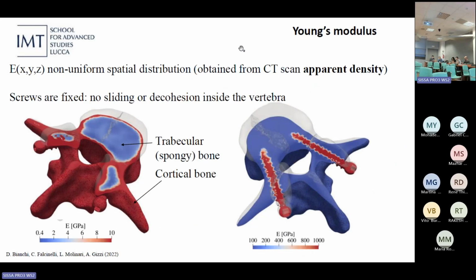Regarding the reconstruction of the Young modulus, this of course is not a uniform material, it is a bone. So we have a non-uniform spatial distribution of the Young modulus. This was obtained from the apparent density from the CT scan, and it was reconstructed via interpolation.